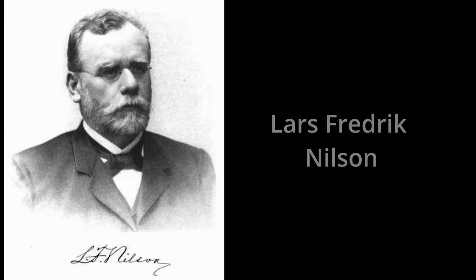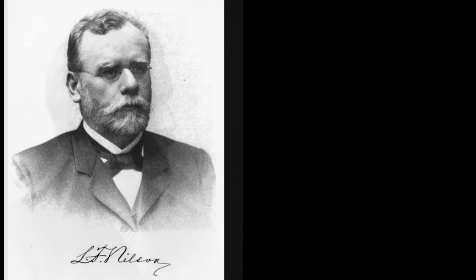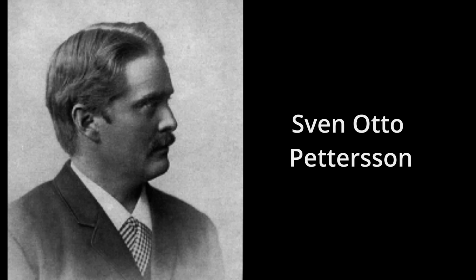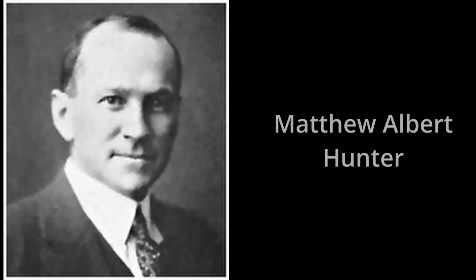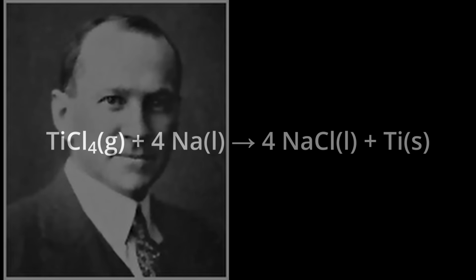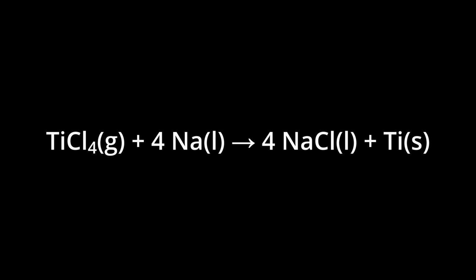In 1887, chemists Nilsson and Pettersson managed to produce about 95% pure titanium by a chemical route, involving chlorine gas and sodium reduction. The first nearly pure titanium, 99% purity, was produced in 1910 by metallurgist Matthew A. Hunter. He invented the Hunter process, heating titanium tetrachloride with sodium metal at red-hot temperatures to finally yield titanium metal. It was a breakthrough, but still not efficient for large-scale production.